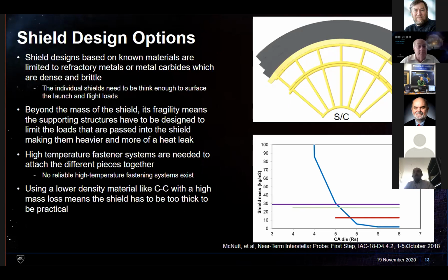So again, at the top side you're limited, material-wise, to refractory metals or metal carbides, which are dense and brittle, so they're heavy. That was part of the earlier study: as this top part of the shield design becomes thousands of kilograms, it loses its intention. So the bottom curve is showing that for different materials, if you're looking at this from a material survivability point of view, you're saying this material has to survive through this hot pulse.